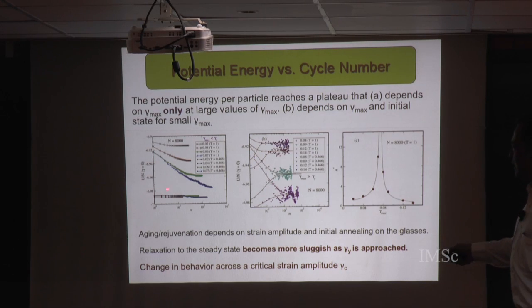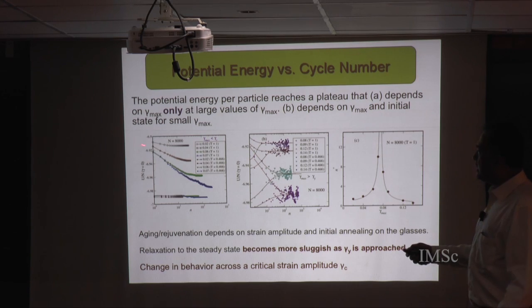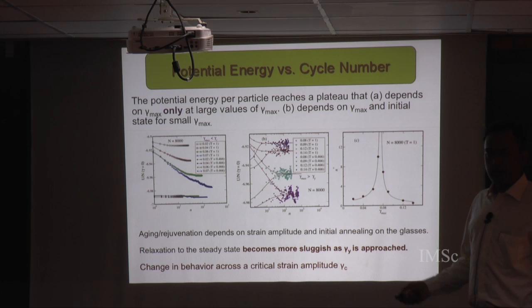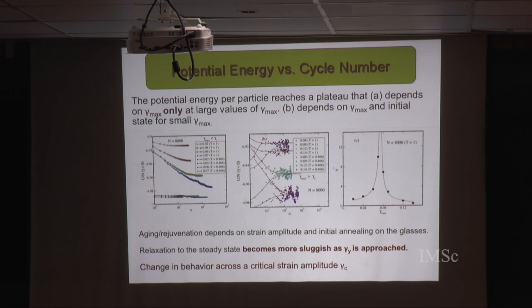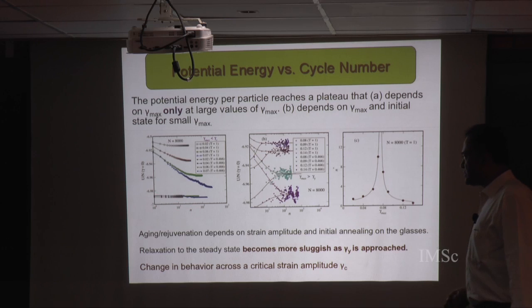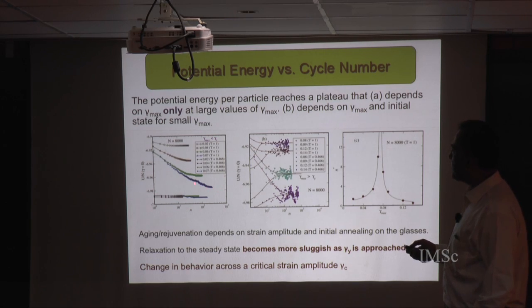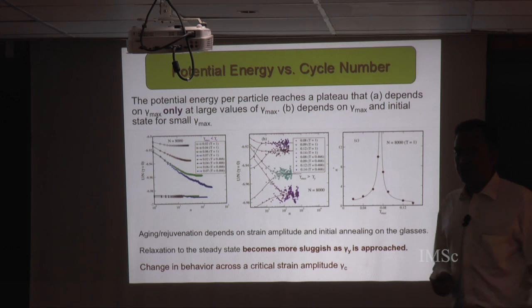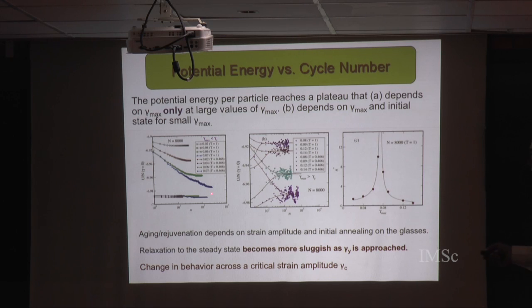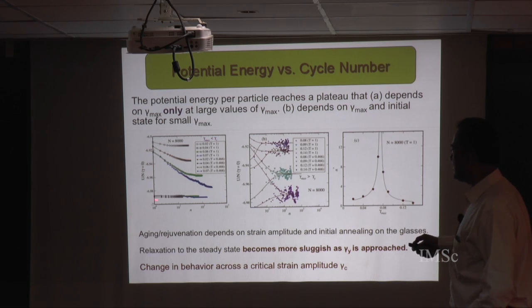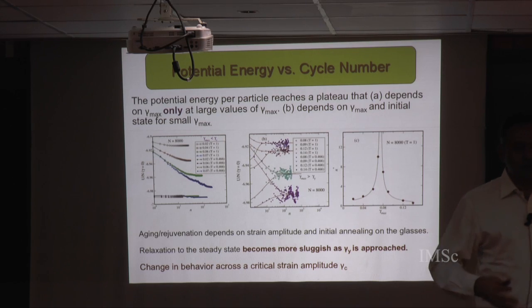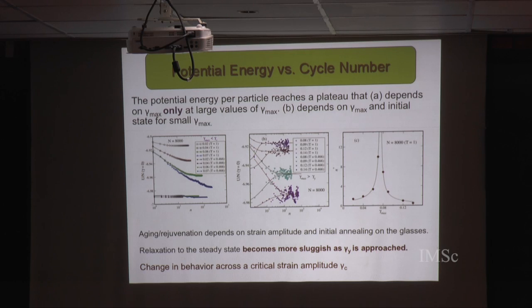As I said, I will always have two glasses: one is the well annealed glass and the other is the poorly annealed glass. For these sets of amplitudes, you do have some change in the energy. The poorly annealed glass gets lower and lower in energy as a function of the number of cycles, while the well annealed glass doesn't show much change. But at the end of whatever number of cycles we apply, the two glasses retain their identities and memory of their initial state, in the sense that their energies remain different.